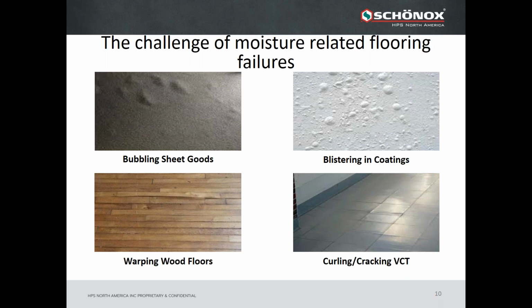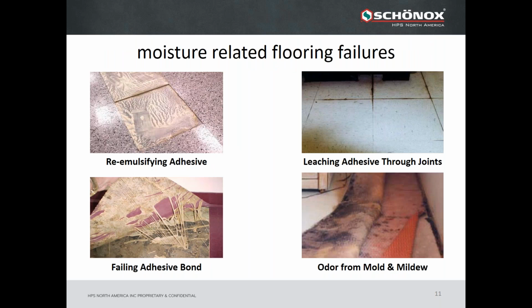One of the greatest challenges facing the flooring industry today is moisture-related flooring failures. These pictures are just representations of situations where flooring has been ruined by high moisture content found within slab conditions. On the left side, on sheet goods, it's typically evidenced by bubbling at the surface from moisture trying to escape from the slab and being trapped underneath the sheet goods. If it's a coating system, you'll typically see blistering underneath that coating system. With a wood floor, you would have some warping from that high moisture. And with VCT, it's evidenced by visual curling or cracking, again from moisture trying to escape from that slab surface.